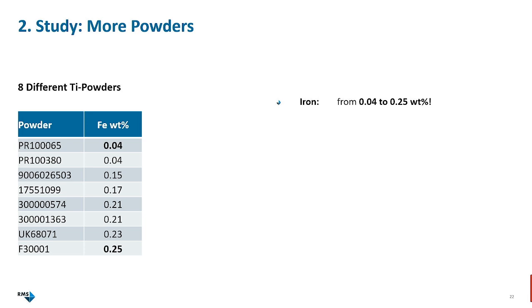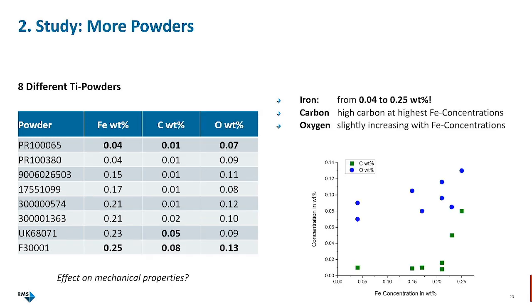Within the second project, there have been 8 different powders investigated. Nominally, they have been the same. In fact, they had been showing some variations. For instance, iron content varied between 0.04 to 0.25, so a factor of 6. Together, the carbon concentration was increased with the higher iron content samples, and oxygen was quite similar for all, maybe slightly increasing.